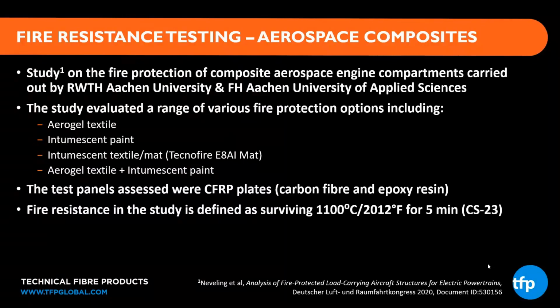They looked at a combination of the aerogel and the intumescent paint. These were carbon fiber and epoxy resin plates, panels, and they ran some fire resistance testing at CS23, which was defined as having a survival of 1100 C, or over 2000 degrees Fahrenheit for 5 minutes. Next slide, please.